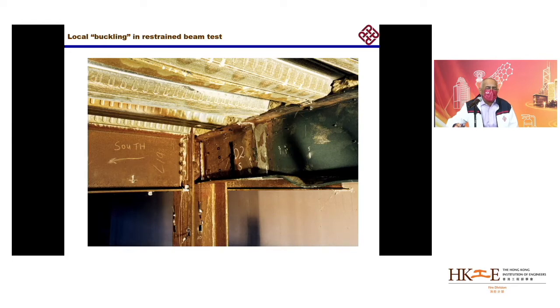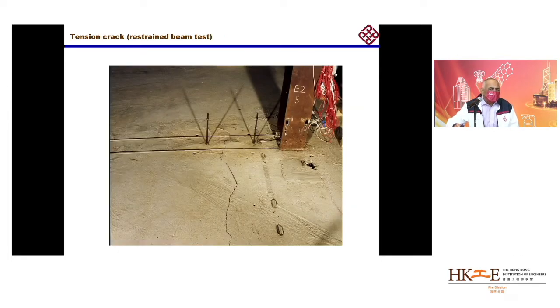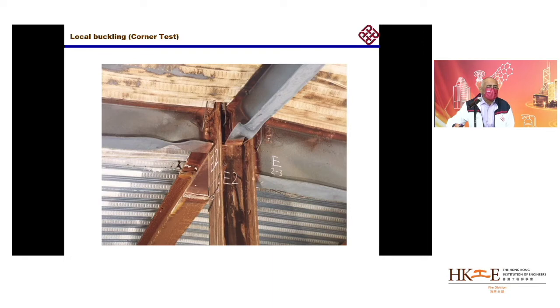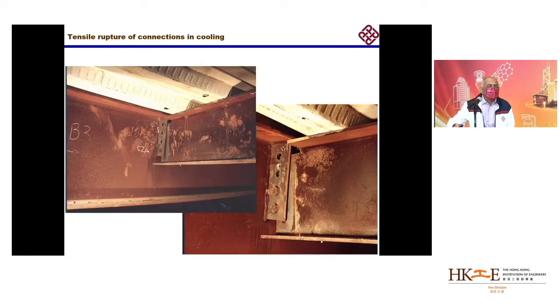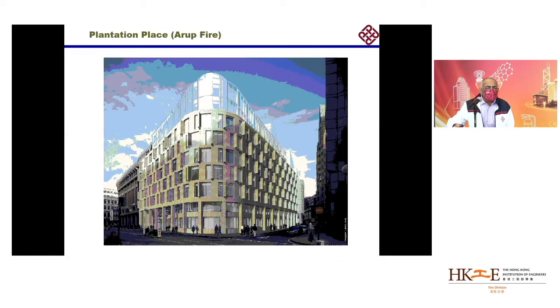But what you see is at very low temperature, the beam bottom flange is buckling, because the rotation restraint is too high, and the top of the slab is also cracked. So you get a bottom flange buckle and a crack at the top because it's trying to bend but is not able to, so it's cracking at the top and buckling at the bottom. And when it cools down, it becomes shorter because there are plastic strains in it, so it pulls off the connections.